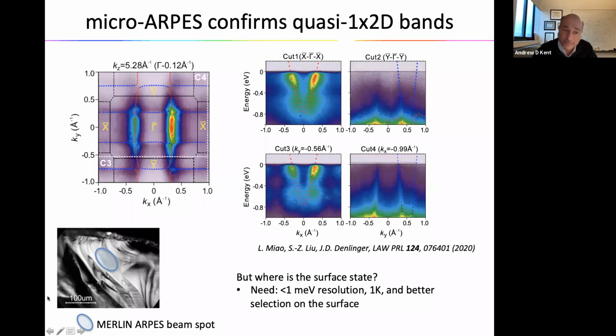Is that coming too? So for temperature in this particular case, if you can't apply strain or do something special, you'd want about 1 Kelvin to have fairly good coherence, to be well up above the critical regime. Yeah, the superconducting state, the typical onset, if I'm not remembering incorrectly, is around 1.7 Kelvin.